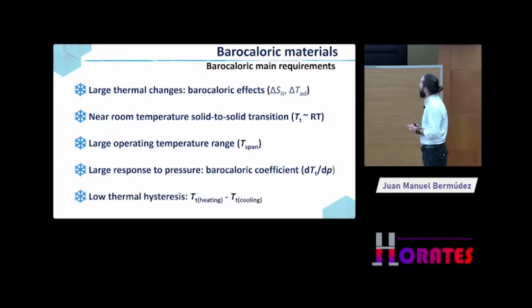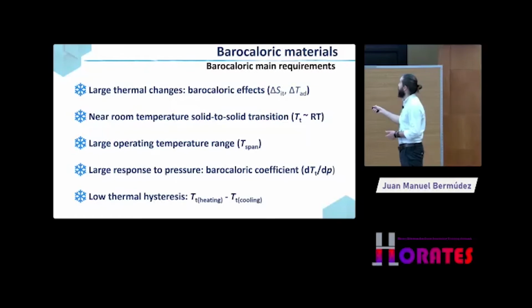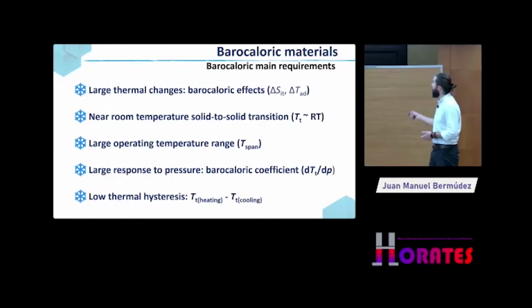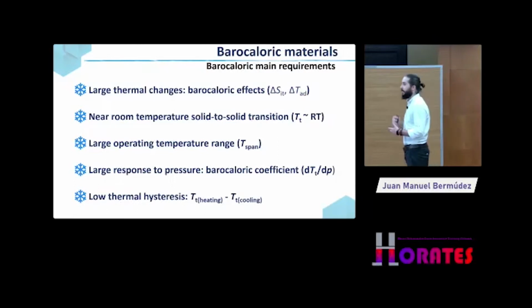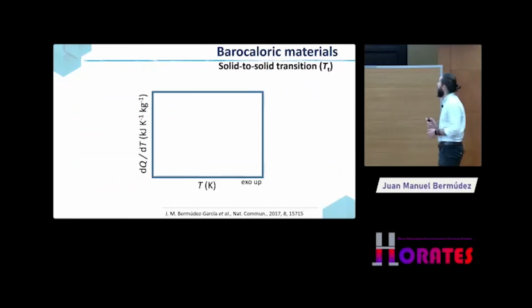And then another important parameter is the thermal hysteresis. You want your material to have a low thermal hysteresis, which is the difference between the transition temperature on cooling and on heating. I will explain that a little bit further later. And the lower this thermal hysteresis is, the more efficient in principle your material will be. I'm going to explain that in a bit.